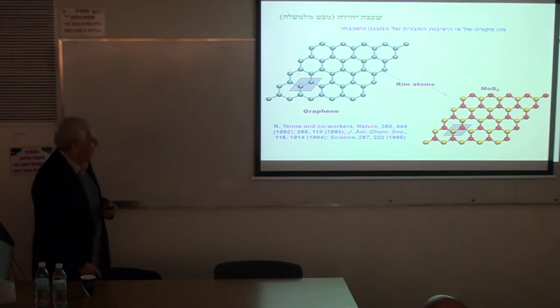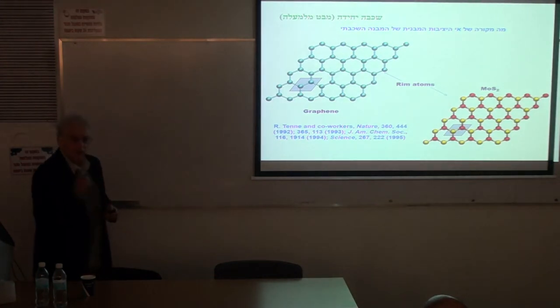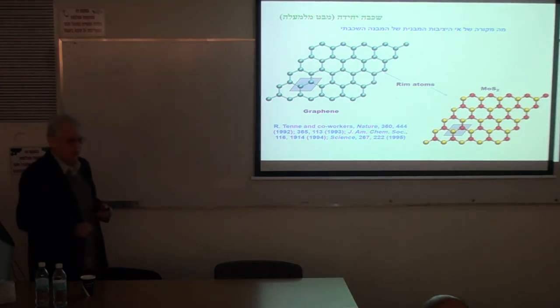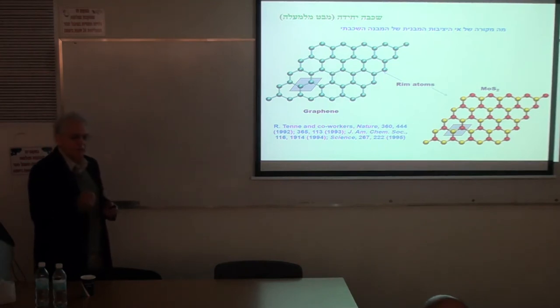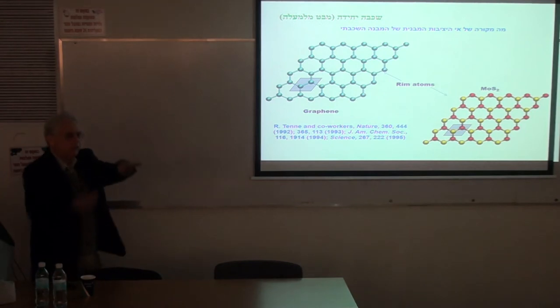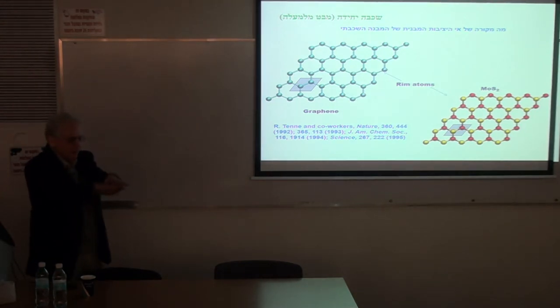And here came my contribution. In 1992, just one year after Iijima published his work, I came out with the idea that molybdenum disulfide will form nanotubes and fullerenes because in the nano regime it suffers from edges, and the edges are too reactive to remain as a flat structure. So these are 2D materials. The 2D materials are all made of layers, like graphene, made layer by layer, and they all suffer from edge effects.